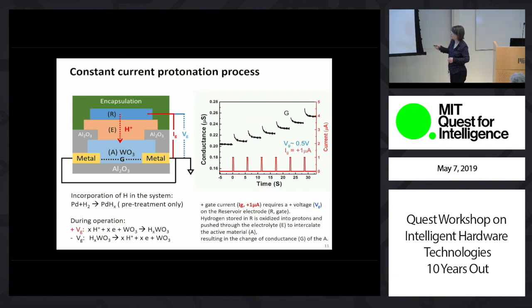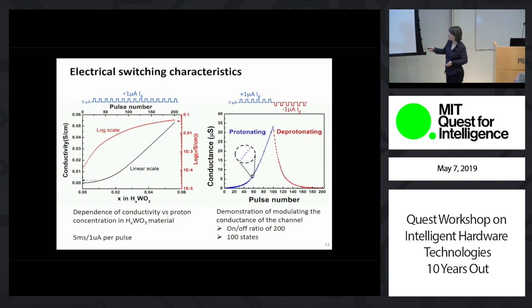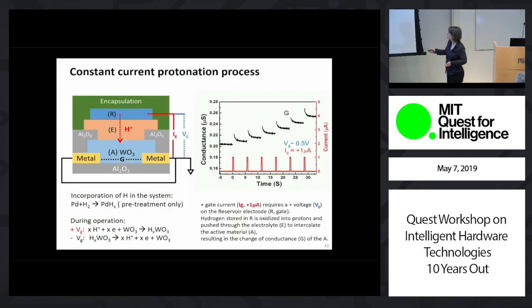And the electrolyte is Nafion. The active layer is tungsten oxide. As we apply positive current at the reservoir, we oxidize the hydrogen, sending protons through the solid electrolyte and the electrons through the outer circuit. Insertion of the proton into the tungsten oxide changes its conductance state.